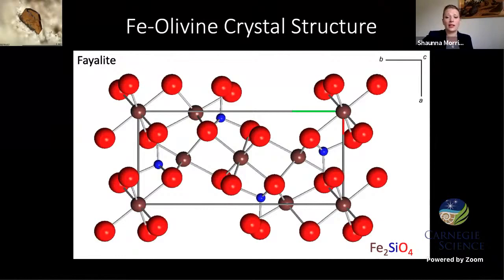What this means is that when I get X-ray diffraction data from CheMin that tells me the size of the crystal structure, I can actually predict how much iron and magnesium is present in that olivine on the Martian surface. And when I do that for the olivine we've analyzed in Gale Crater, I found that it contains significantly more iron than what we generally observe on Earth, which is interesting. And it tells us one of two things: either the Martian olivine crystallized at a lower temperature than what we generally see on Earth, or that the magma it crystallized from had a significantly higher iron component than what we generally have on Earth.